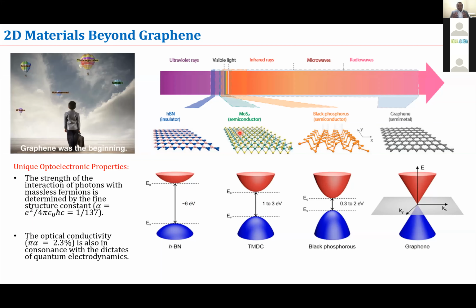And then we also need some material. There are some materials whose band gap is between the zero band gap material graphene, which is here, and the insulating material boron nitride. So these are transition metal dichalcogenides, and these are two-dimensional semiconductors, and their band gap varies from 1 to 3 electron volts, and they are just like a normal semiconductor, for example, silicon. They behave like semiconductors. However, they are atomically thin because it is a three element material. You can see molybdenum and 2 sulfurs. So you have a molybdenum or tungsten that is sandwiched between sulfur on top and on the bottom. So it's a 3 atom thick material. However, the thickness is only about 0.7 nanometer, whereas the graphene or boron nitride thickness is only about 0.34 nanometer.